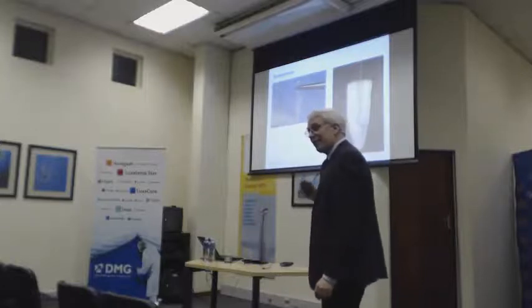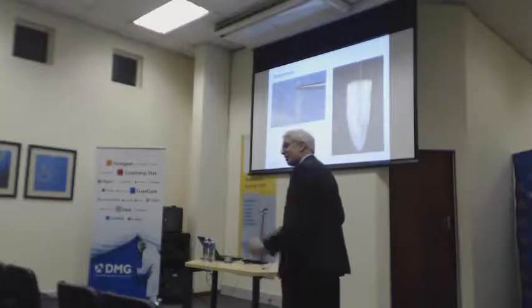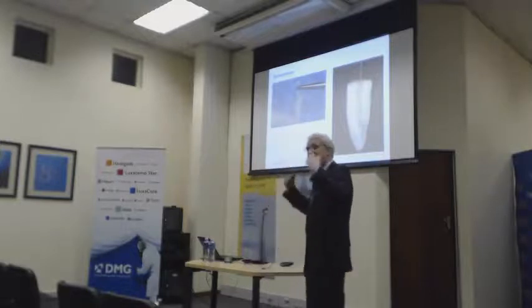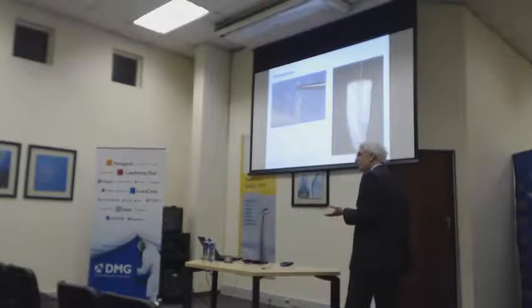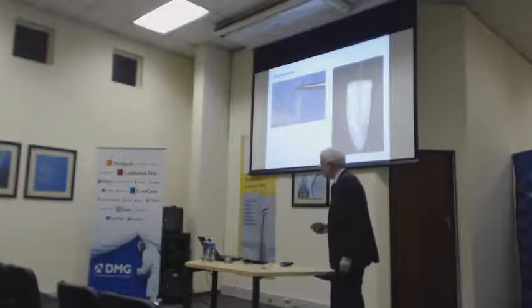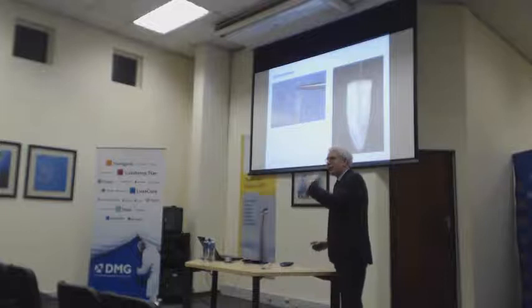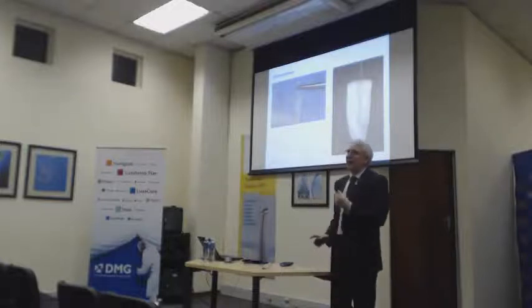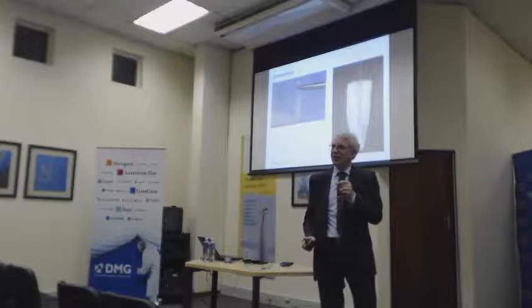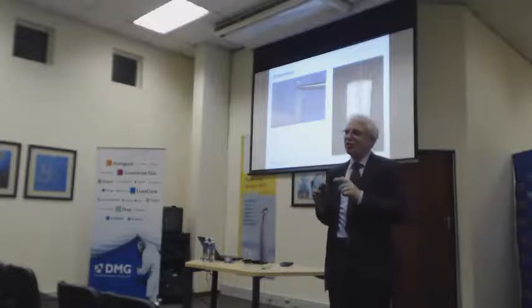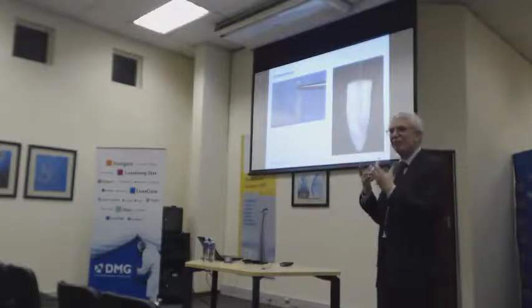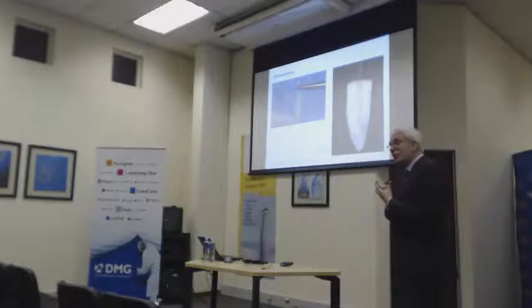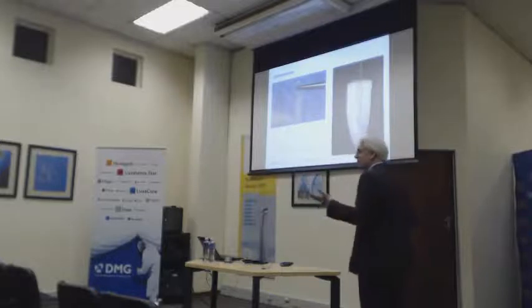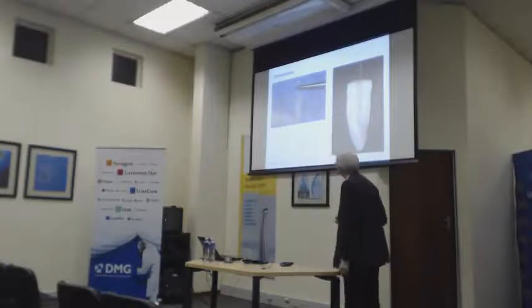if you try to get the cement down in the root canal, the second it touches the walls and gets into contact with the polymerization accelerator, you have 20 seconds. And if you place the post later than that, it may already start to gel up. And a gelled up cement is not giving you the same adhesion as a very nice flowable cement would. In a worst case scenario, you don't even get it down because it's so gelled up that it doesn't flow around and you can't make sense of it.